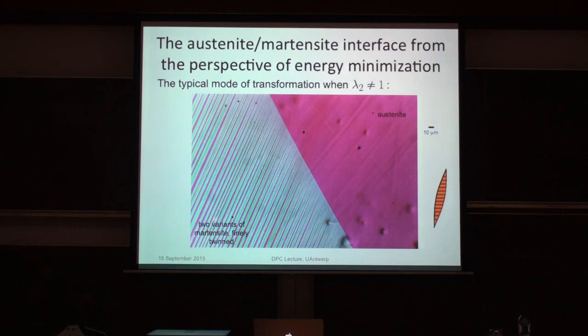It's that there's a tiny interfacial energy, kind of like a surface tension on the boundaries of those bands. So if you add more and more bands, you add more and more interfacial energy. You drive the elastic energy to zero. Of course, if you made them very coarse, you wouldn't have much interfacial energy, but you'd have a large elastic energy. And what this picture represents is the compromise between those two. Okay? So it's a compromise between interfacial energy on these bands and elastic energy in this transition layer.